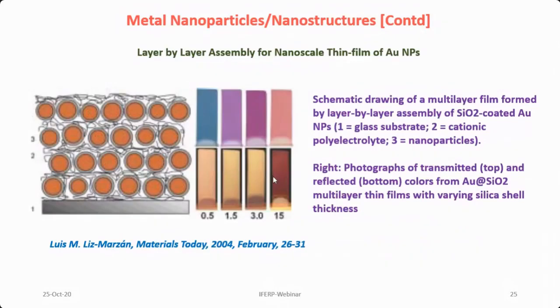This is another paper in Materials Today in 2004, where they have used gold nanoparticles in a layer by layer assembly they have created on a glass substrate. And then they have used cationic polyelectrolyte, because each gold particle acts as an electrode. Then they have provided a kind of electrolyte also in between. And these gold nanoparticles are coated with silica, SiO2. Actually they are core shell gold nanoparticles. In that, core is gold and shell is silica, and shell thickness they have varied, and as shell thickness varies, you see the change in color of the substrate.